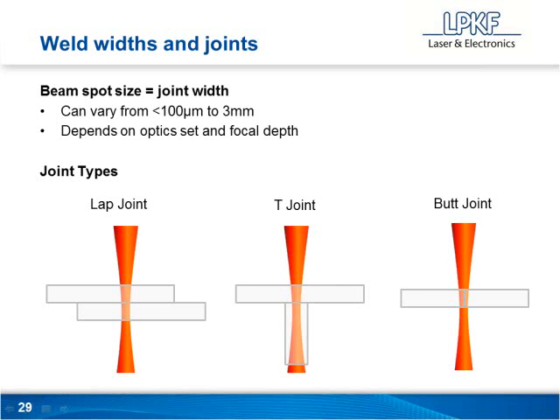Clamping will hopefully overcome the rest of it, and then the laser welding process, although dependent on the plastic, can be finicky sometimes. We have seen some good results overcoming gaps. So yeah, it depends again whether it's hard or soft. I mean, if it's soft, it's going to squeeze together. But we have seen issues where we're doing a butt joint in a flexible, and of course, if you squeeze it together too hard, it collapses, and you do get a lot of bulging.